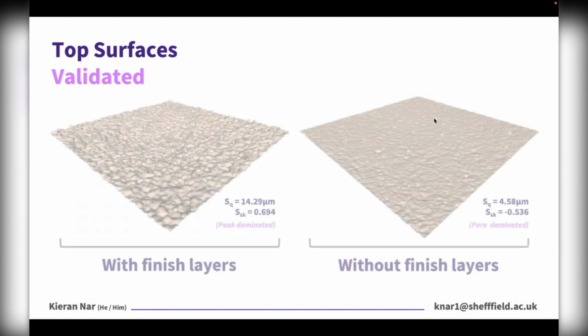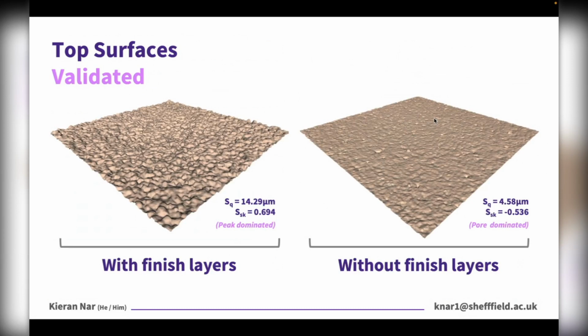And there was a really straightforward way for me to validate this experimentally, and that was to build more samples and make sure to hit the stop button on the machine as soon as the final build layer had been sintered, to prevent any finish layers at all from being subsequently deposited. And as you can see, there was a drastic difference between top surfaces built with and without finish layers. The latter were instead found to be pore dominated, which you can kind of make out on the screen, and the resultant surface height, I'm sure you all agree, was significantly reduced.